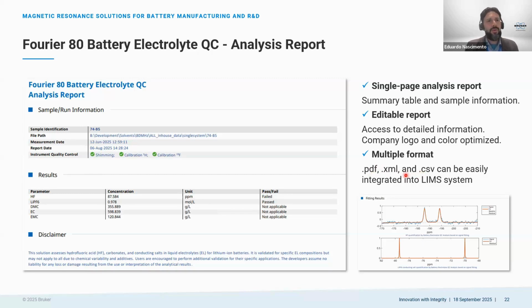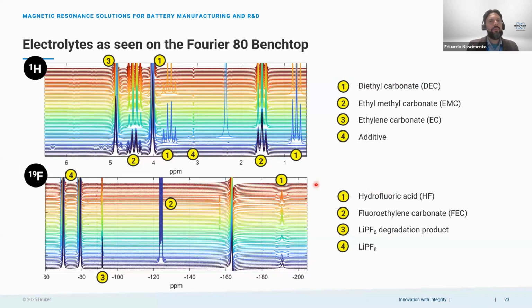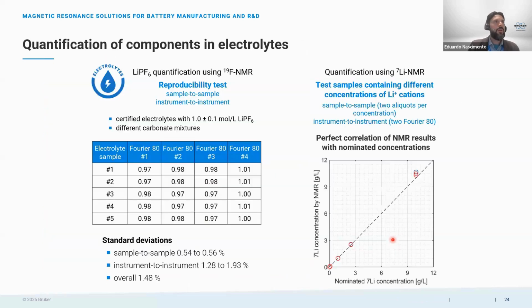This is an example of an electrolyte sample that was analyzed with our system. You can see here the typical carbonates, DMC, EMC. Of course, depending on the additive and the concentration of the additive that you are working with, you can also see the signal here. In the fluorine spectrum, you can see the HF, another additive here, the FEC, and you can see the LiPF6 and some degradation compounds.